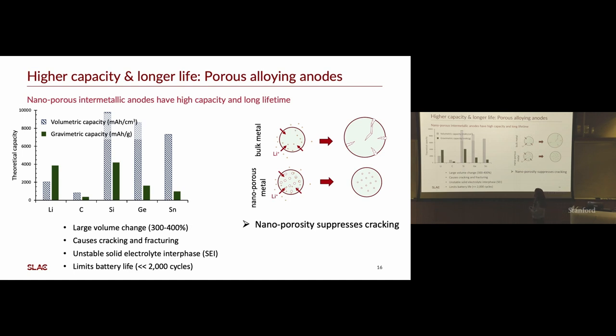So the problem with these silicon, germanium, and tin anodes, which alloy with lithium, is when they alloy with lithium, they have this large volume change that allows them to accommodate this large capacity. But if you think about these large volume changes as you cycle many thousands of times, no material can withstand that amount of 400% volume change, 2,000 times. So it causes cracking and fracturing, very similar to what we saw actually in the cathode, but more extreme. And it also creates this unstable interface layer between the anode particles and the liquid electrolyte. And so you're constantly having to regrow this interface layer as you expose more silicon or tin to the electrolyte, because the electrolyte is not stable against these particles.